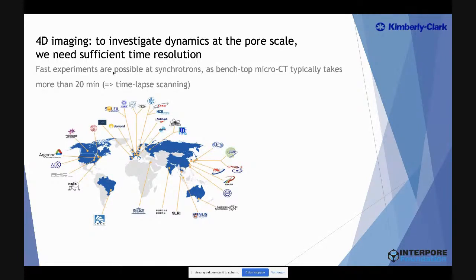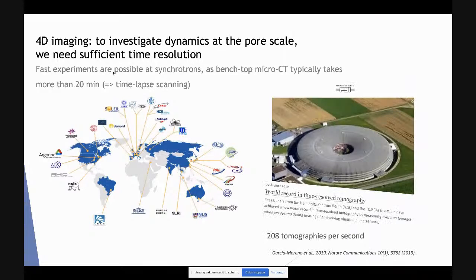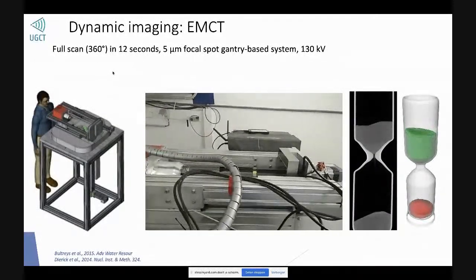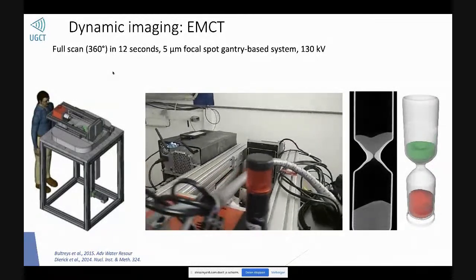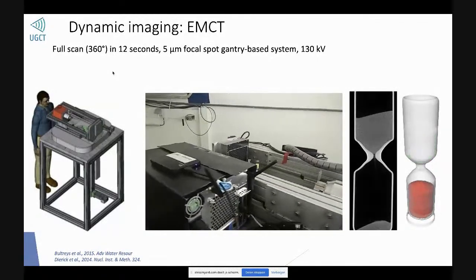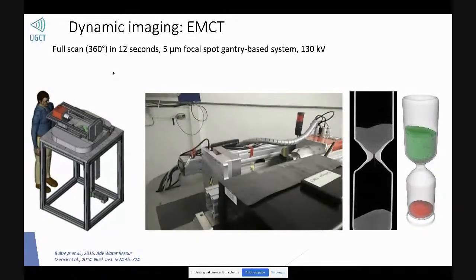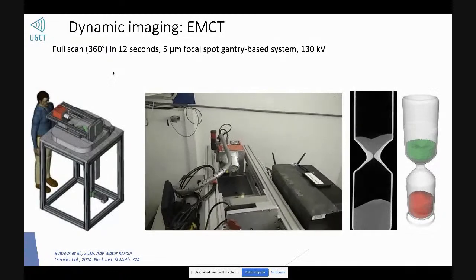But if you want to go for fast processes, during one scan everything needs to be stable, so you preferably want fast rotations. This is possible at the synchrotron. Here, I found an article of work at PSI where they did 208 tomographies per second, but you do not always have full-time access to a synchrotron. So we developed a dynamic scanner, our environmental CT scanner, where the source and detector are rotating around our sample, and where we do a full scan in 12 seconds with a focal spot of 5 micron.